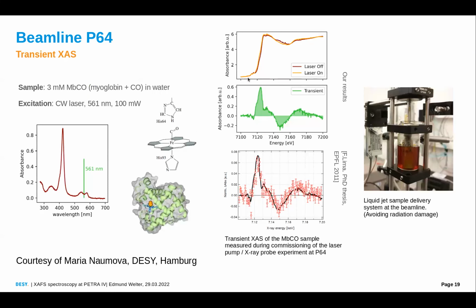And then you see here some differences between the laser off and laser on spectra, the transient spectrum here compared to the same spectrum which was published in 2011. But that certainly took days to measure, with a lot of noise. You see the quality is much better and the time was much smaller.